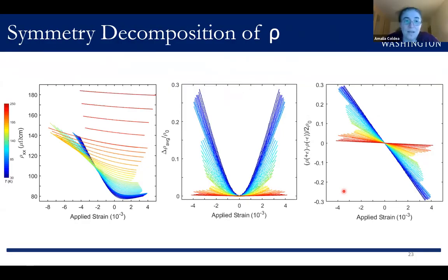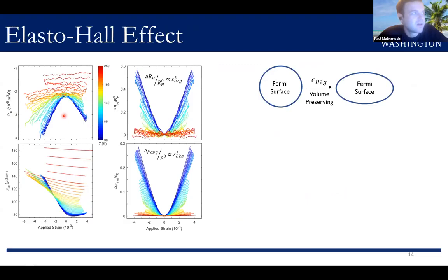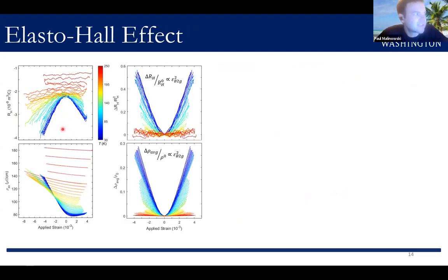Well, I just thought it's good to think about when you measure Hall effect, things become more complicated. And maybe you have more information there you can extract from the data. Yeah, so the data that we show for the Hall, like this data, for instance, we actually do anti-symmetrize the data. So we measure a positive and negative field and sweep strain, and then we anti-symmetrize that set of data.